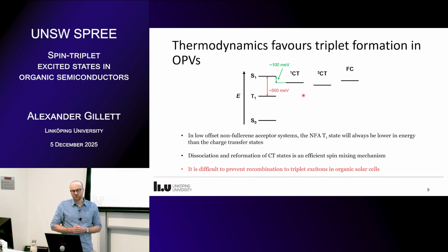But then with our organics, we have quite a large singlet-triplet energy gap. This means you have a lower-lying triplet state, let's say on the order of half an eV below the singlet. And we know that state is dark. The problem now is that, through our charge generation via the CT state to free charges, and recombination back into the triplet CT state or singlet and so on, we have quite an efficient spin mixing channel. So we can efficiently populate the spin triplet charge transfer state.